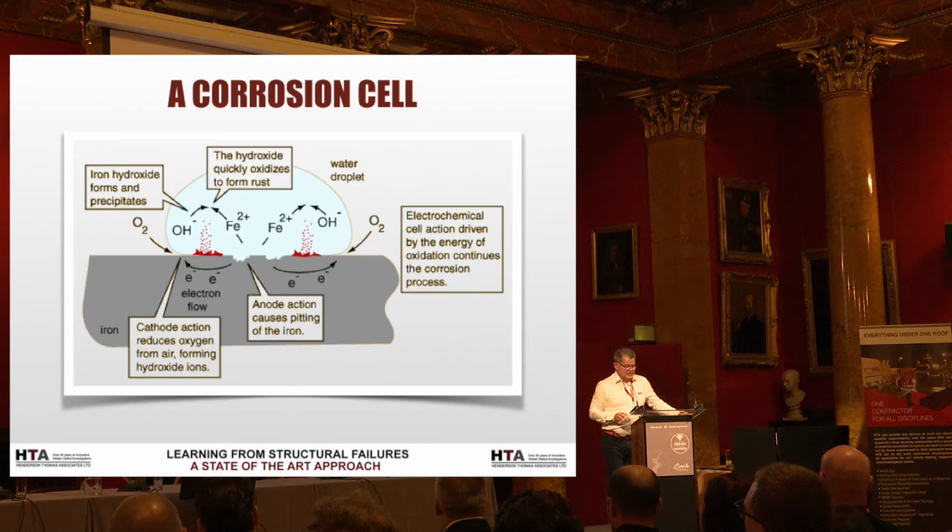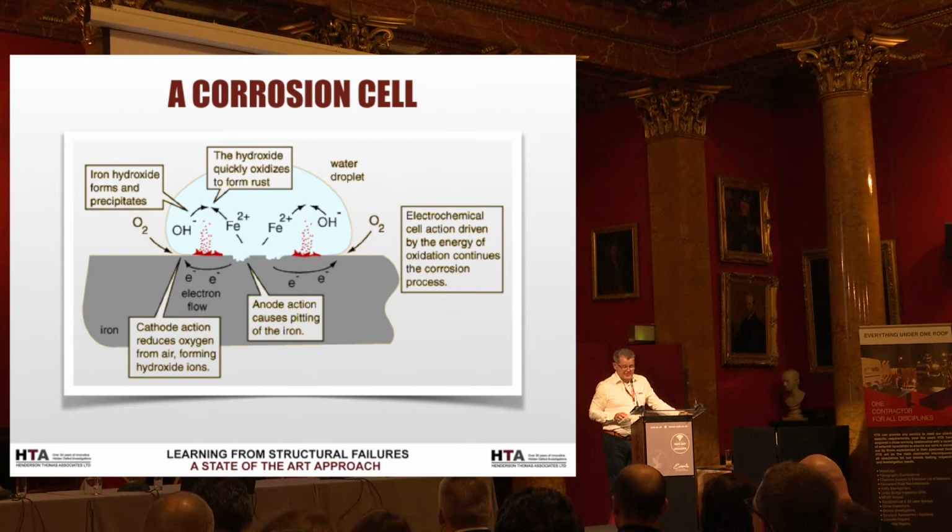At the time, the technology on cathodic protection on concrete was in its infancy, and the Lancashire County Council said, we're not going to electrocute our concrete, which was the thing that people said about cathodic protection back then. And so they just did standard repairs. Within 15 months, all the repairs were fine, but all the areas around the repair, a bit like a halo effect, had caused masses, two, three times as much corrosion. If you keep going out patch repairing it, you'd have ended up repairing the whole of the police station.